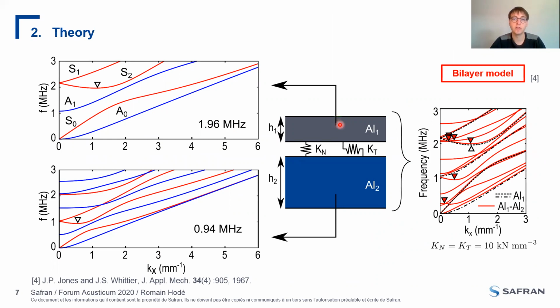the dispersion curves for 2 aluminum plates that are fully decoupled. So in the case of just a single aluminum plate, we will obtain these dispersion curves. And in the case of a thick aluminum plate of 3 mm, we have these other dispersion curves with a ZGV mode around 1 MHz. But we can also mechanically couple these two plates with two distributions of interfacial stiffnesses, normal and transverse, that are used here to model the adhesive. And we can obtain the dispersion curves for this mechanical coupling between the two aluminum plates.